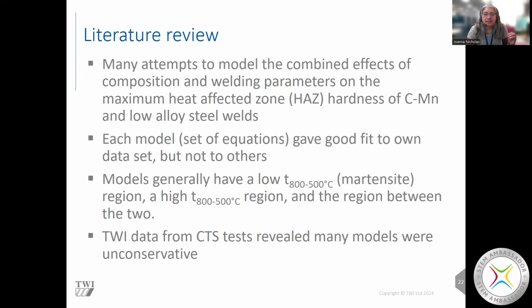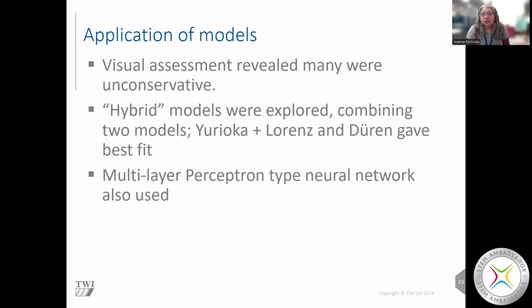They did have that same approach where we had a low 800 to 500 cooling time, so it's 100% martensite, a high 800 to 500 cooling time, 0% martensite region, and the region between the two. And the data that we got said that some of the models didn't really work very well. You could do that visually just by saying, well, okay, if I've got a one-to-one line, how do they look? And we've looked at the individual models and combination of models and a neural network.